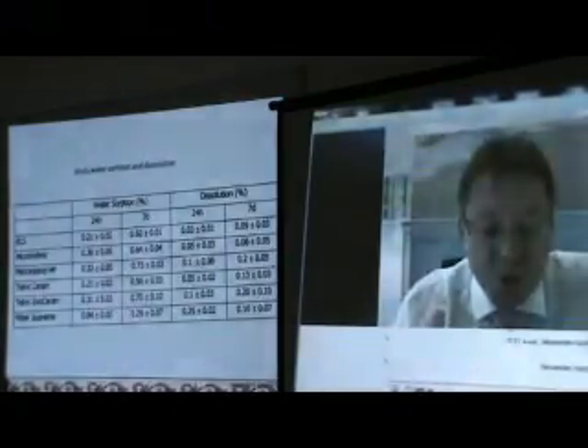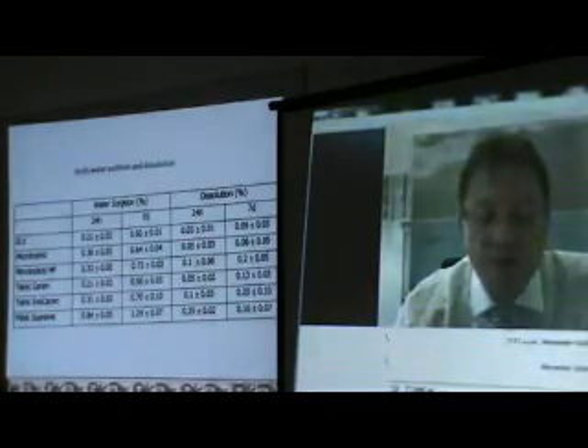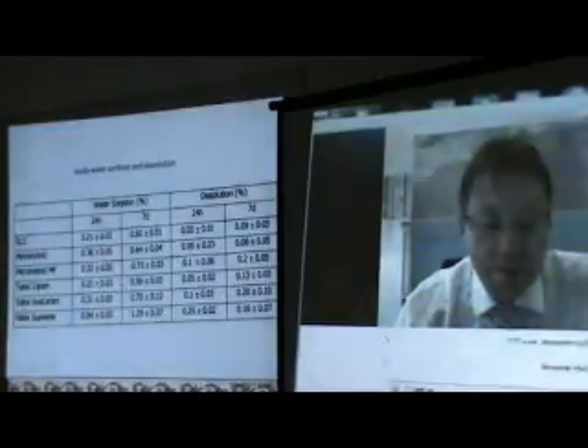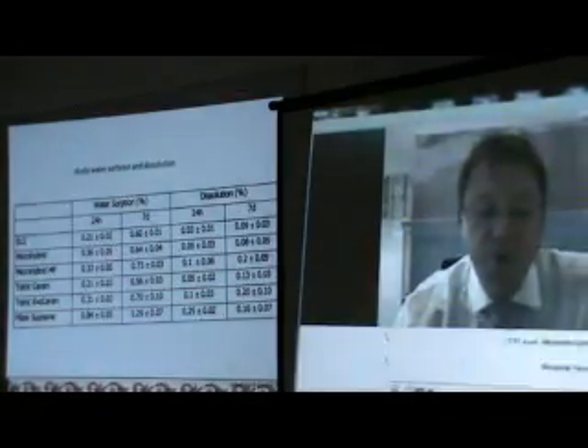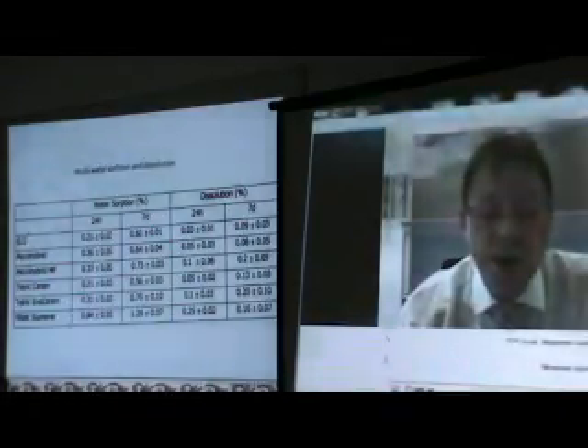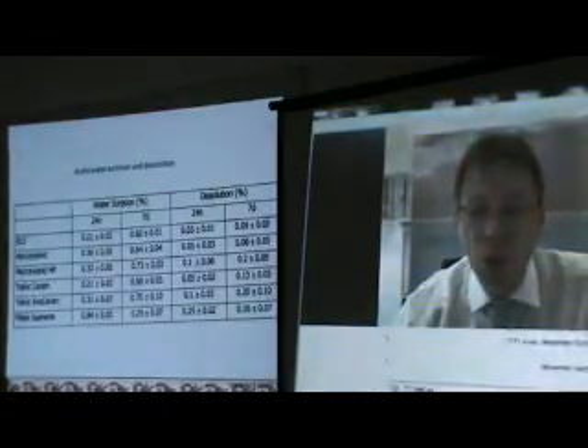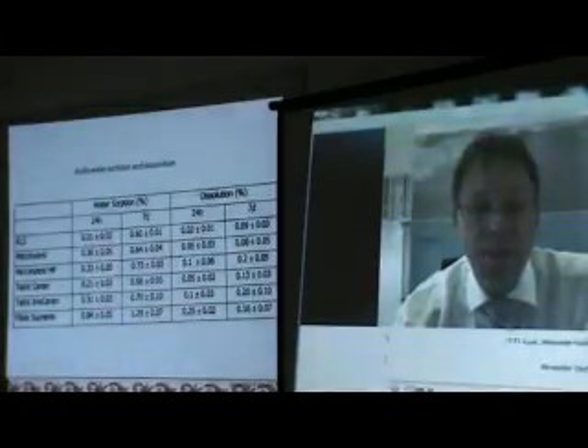the composite. So on this result, if you look at water absorption, 7 days, you see that ALS has a value of only 0.6%. Microhybrid composite from Cerenco 0.64, and if you take an example, for example, Vitex Supremia, there you have with the same study 1.29% of water absorption. You see there are differences in the water absorption. So with ALS and microhybrid, you can guarantee a product with a very low water absorption and therefore a very good color stability. And also an advantage on the toxicology side because there will be also less leakage of critical substances. Next slide, please.